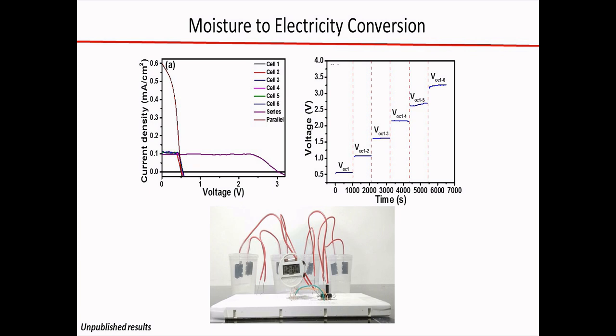When we connected them in parallel, the current added up, and we could get around 0.6 milliampere per centimeter square. When we connect these devices, the voltage sequentially increases for all 6 devices - this is 2 connected, 3, 4, 5, and 6 connected devices.